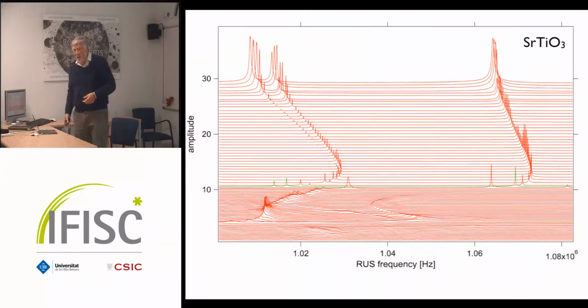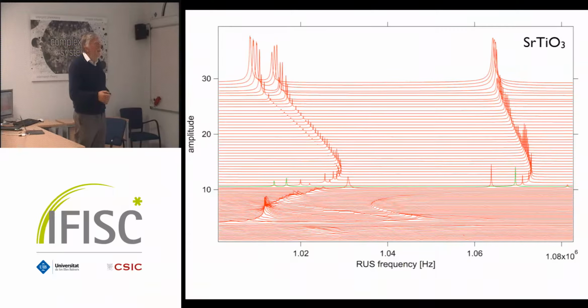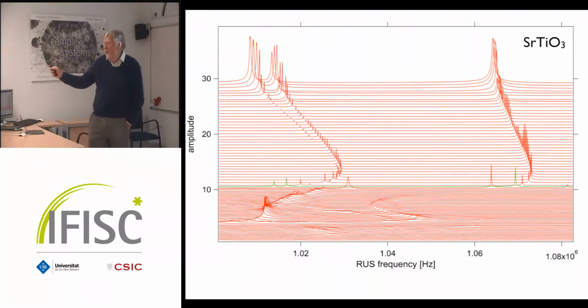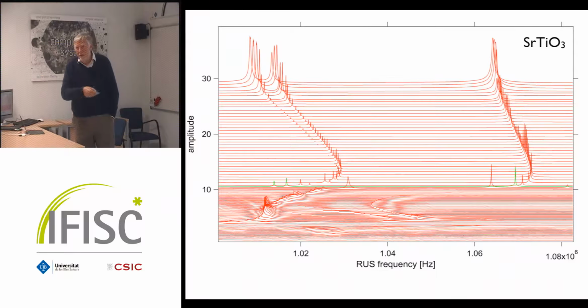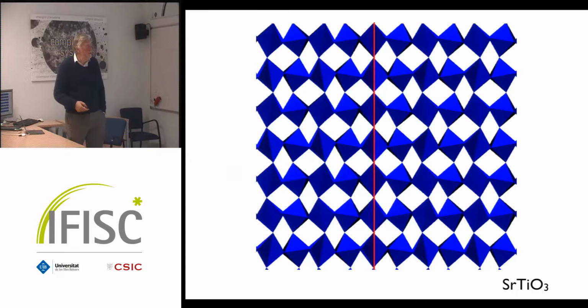And just to show that it works, here are these resonances in strontium titanate, which is not quite a ferroelectric material, but it's not polar in principle. The material is not polar. Here's the phase transition in strontium titanate, and here's the resonance frequency, which changes. And then at low temperature, you can suddenly see there are all sorts of peaks coming up in a very complicated structure. And that is when these interfaces suddenly become polar. So at high temperatures they're not, at low temperatures they are. And, you know, so that gives you a few PRLs.